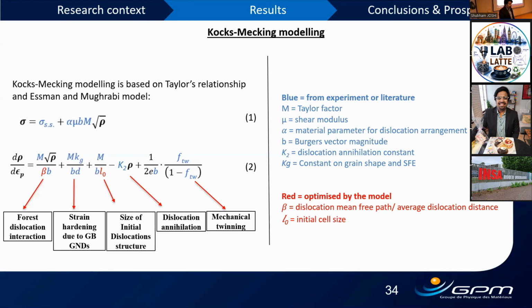So for me, it is evident that you obtain the same result, because you are using this test to identify and you validate your model with this same test. So my question is, is it possible to validate the model with other observations? For example, in your report you have plotted the dislocation density evolution from the model. Can you compare this result obtained from the model to experimental data, for example, to further validate this model?